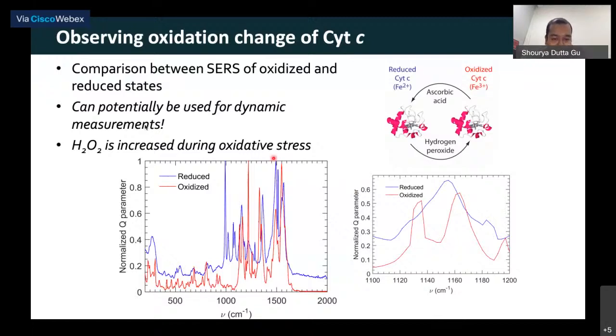So this is a typical Raman spectrum that you get. So horizontal axis is the wave number, vertical axis is the Q parameter. And if I zoom into this certain part of this spectrum, what I see is if I have the oxidized one, I'll see 2 peaks. If I have the reduced one, I will see 1 peak. So by looking at this change, I'm able to say whether the cytochrome C on my particle are oxidized or reduced. So this is one way of doing diagnostics with SERS.